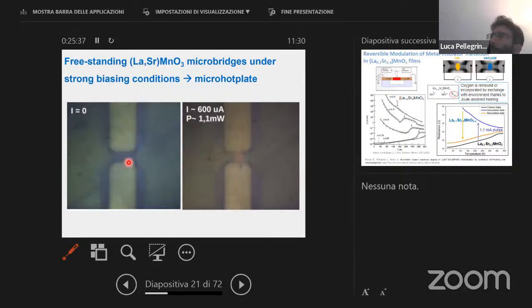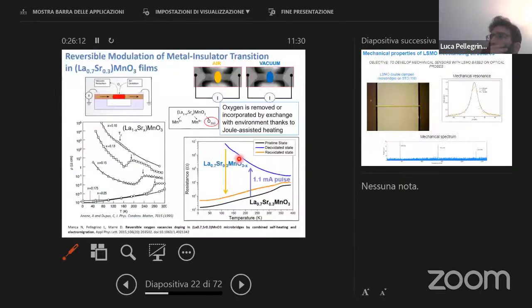This is a quite short microbridge, and I would like to show that you can heat up the microbridge in air conditions, and you have light here due to the high temperature that you have in this place, and you flow about 600 microamperes. You have about 1 milliwatt of electrical power inside the structure, and you have red light, which is due to the fact that you are heating up the sample. You do not oxidize because you already have an oxide, so you can work at room temperature. So this can work as a micro hot plate. And I will now show you how we can use these heating properties of these microbridges to make some kind of memory, which is quite interesting to me, because you can heat up the sample, as I said before, both in air conditions and also in vacuum conditions.